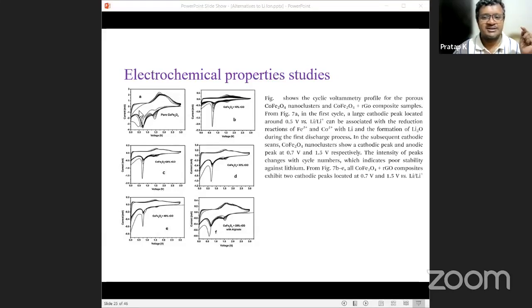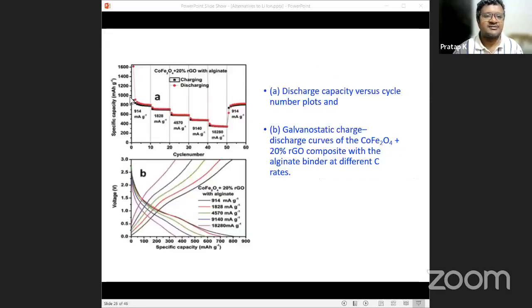So this graph is for pure cobalt ferrite. This is for 10% RGO, 20% RGO, 30, 40, and 20% RGO with alginate binder. So 20% RGO plus alginate binder is showing a clear area where it can store the energy. So this is about charge-discharge plots.